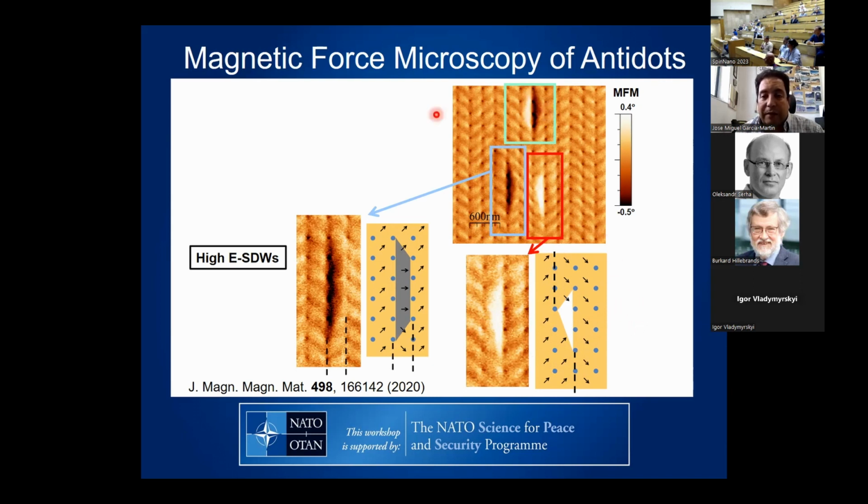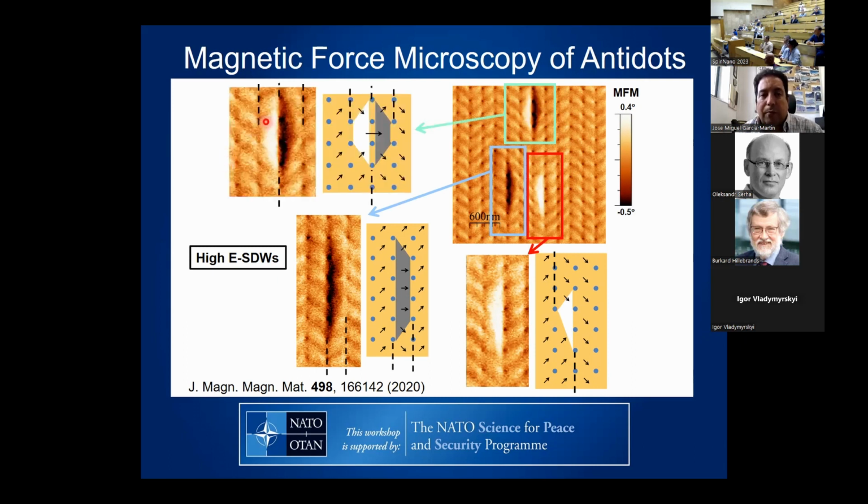And now, finally, the dipolar contrast region is composed of a bright high energy superdomain wall and of a dark high energy superdomain wall. So you can see the bright region, this 1, 2 low energy domain walls, and for the dark region 1 and 2. So at the end, we have 4 low energy superdomain walls in this region with 2 high energy superdomain walls.